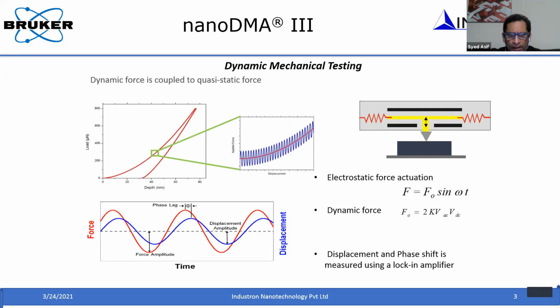Okay. So in nanoindentation, as you are all familiar, what you get is the load displacement curve, and that we call the quasi-static test, where you apply a load and measure the displacement as a function of the load. The important part is that you have to measure the stiffness of the contact, which you do by analyzing the unloading curve. That is where Professor Prita Pant mentioned that if you do it over a period of time, you'll have problems with drift. Another important aspect is that with viscoelastic material, these unloading curves behave differently, and depending upon the portion of the unloading curve that you take to analyze the stiffness, you may get a different stiffness, depending upon what percentage of the curve you take. So there will be a lot of problems when you have a viscoelastic material. Some of these things she already presented.